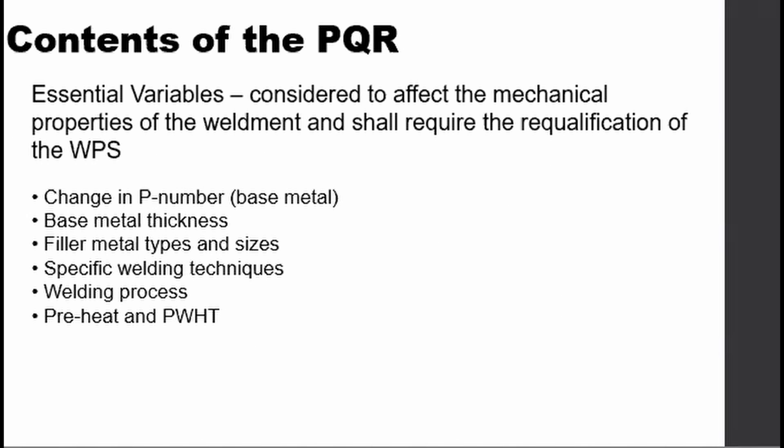But how does the PQR differ? Here are the contents of the PQR. Note that the contents vary depending on the governing codes and standards. Note also that you may have multiple WPS qualify a single PQR, or multiple PQRs qualify a single WPS. Depending upon the codes and standards, there are three variables that need to be identified. The first is the essential variables, which are considered to affect the mechanical properties of the weldment and shall require requalification of the WPS should any of these parameters change.